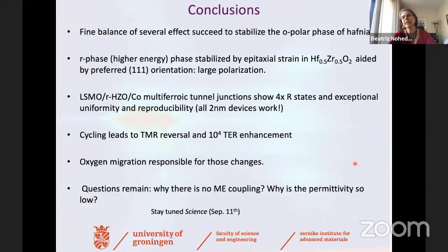So normally in an epitaxial oxide, we put a lot of effort into investigating the growth mode. And we try to grow layer by layer and as flat as possible, as atomically flat as possible. But in hafnia, this doesn't work because you really need to keep the grain size small. So nucleating particles on the substrate actually works better.